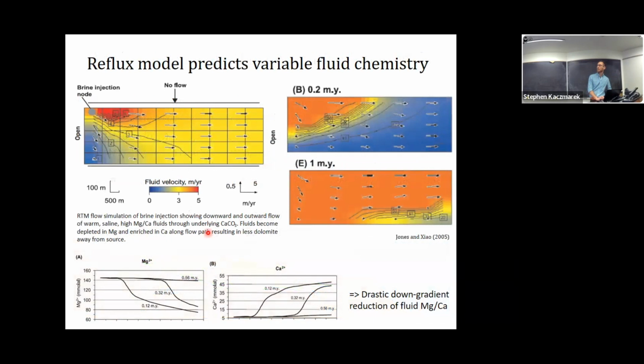The reflux model predicts some stuff. These are some reactive transport models done by some former colleagues of mine at ExxonMobil Upstream Research. Basically what they did is they used these coupled chemical hydrological models to test reflux dolomitization. So they injected a brine into this 2D model, and they showed how this brine fluxes downward through the underlying sediments and dolomitizes.